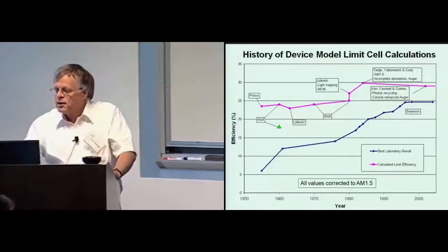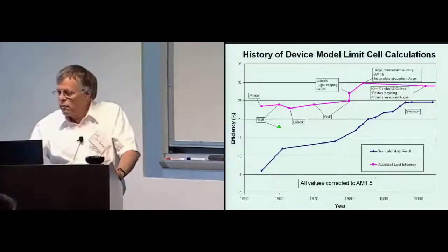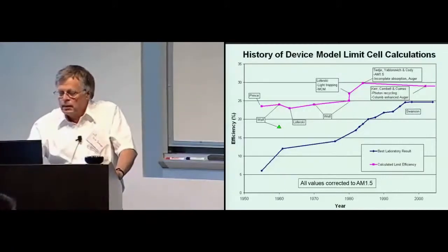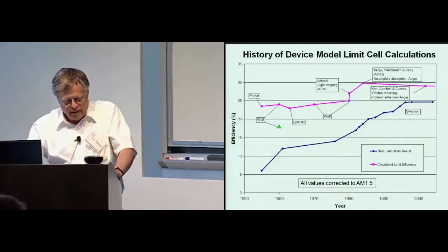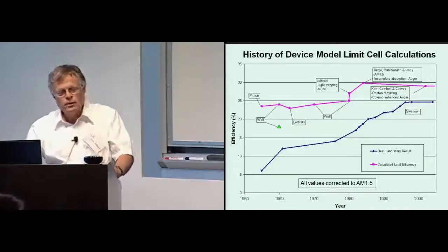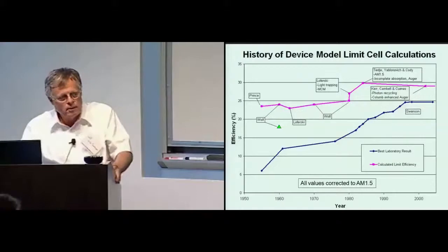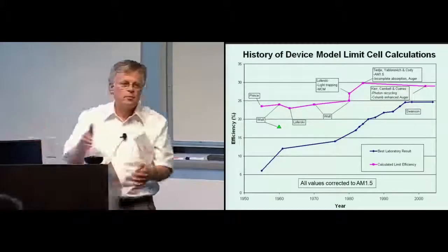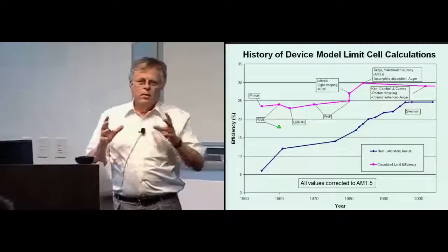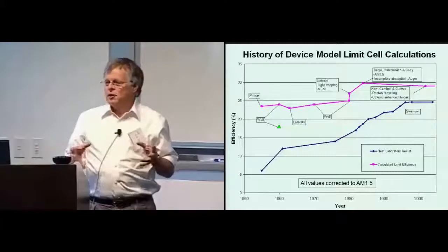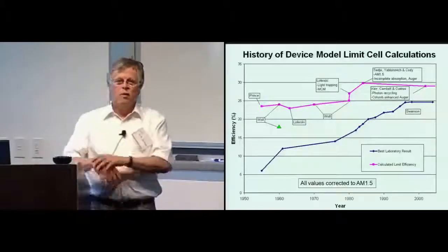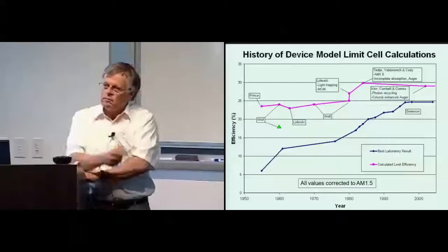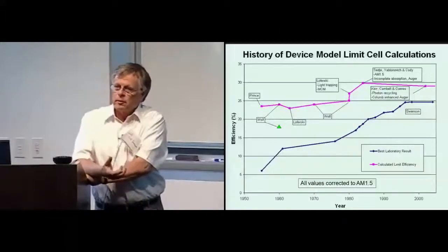So that's kind of where it stood for a while, and then the idea that the recombination in the cell should be limited by radiative recombination came in. If you look at all of the papers prior to that, the minority carrier lifetime was a phenomenological number. They would pick something like 1 millisecond. That was the recombination lifetime for minority carriers.